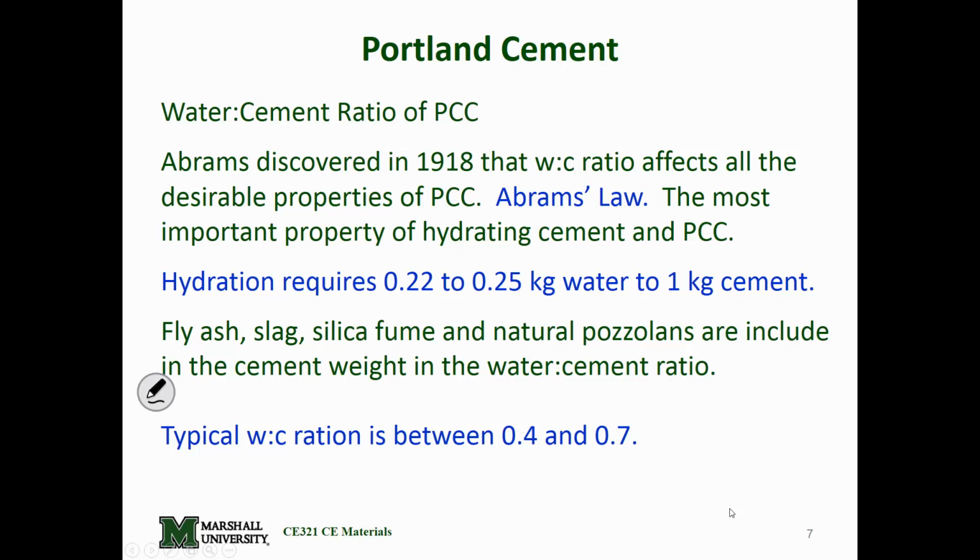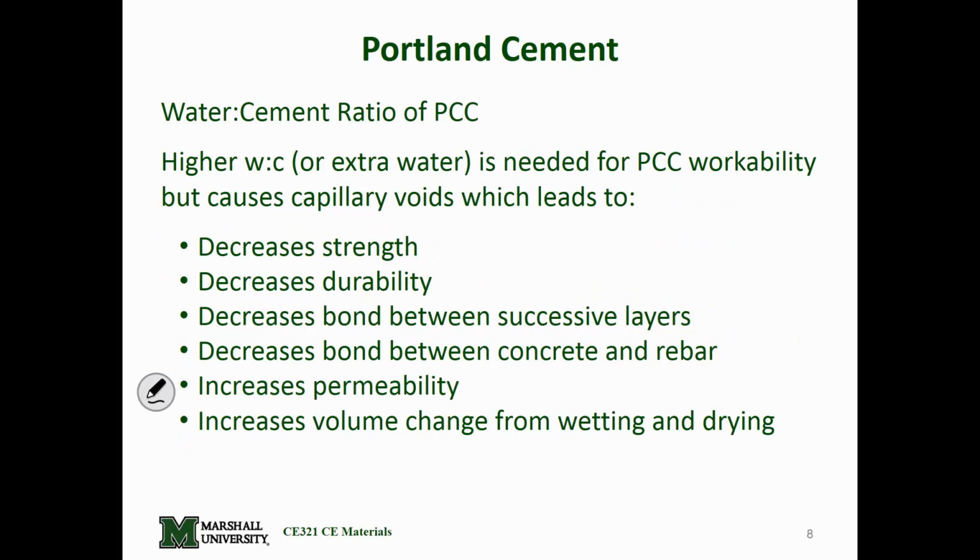So you've got to keep those two sets of numbers separate in your mind. One's for hydration and one's for typical concrete, with extra water for workability. Water-cement ratio, like I say, is very critical for us. As the water-cement ratio gets higher, i.e. we get more water in there than we should have, it decreases strength, decreases durability, decreases bond between layers, decreases bond between the concrete and the rebar. It increases the permeability, and it increases the chance for volume change. It does absolutely everything wrong we don't want to happen to our concrete. So we really have to keep track of our water-cement ratio.